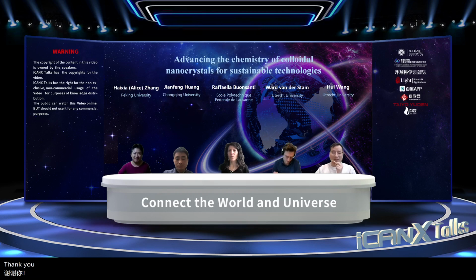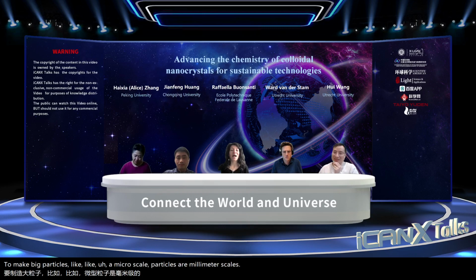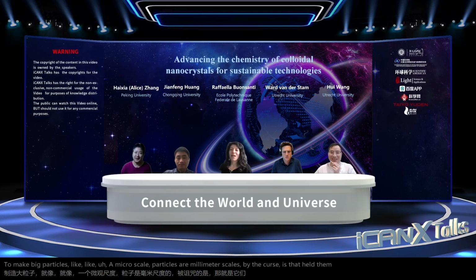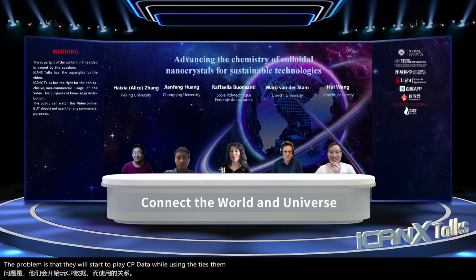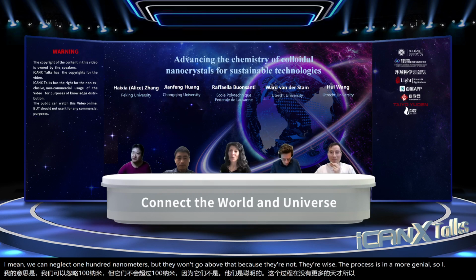Thank you. Another question: I learned from your slides that colloidal synthesis is very controllable. We can control the shape, and using colloidal synthesis we can synthesize very small particles. I just wonder if this synthesis has a limit for making big particles, like micro-scale or millimeter-scale particles. Is that hard? Or is the problem that they start to precipitate while you synthesize them, so the process becomes highly inhomogeneous? I would say that maybe we can make particles of around 100 nanometers, but I won't go above that, because otherwise the process is inhomogeneous. So I would use other methods at that point.